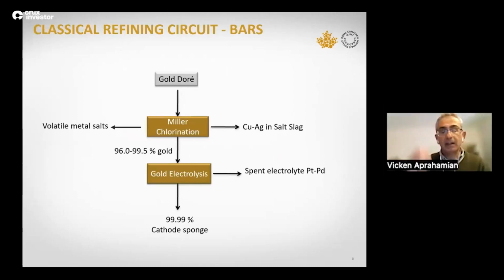So this is a representation, a skeletal flow sheet showing a classical refining system that's used by reputable refiners. Most of the larger refiners still use this technique. It's a 2-step refining of the gold doré, which is first melted in a furnace, and chlorine is introduced to separate away everything from the gold. And this is the Miller chlorination process. It allows recovery of copper and silver in a salt slag, whereas every other metal is mostly volatile and is drawn away into the exhaust.